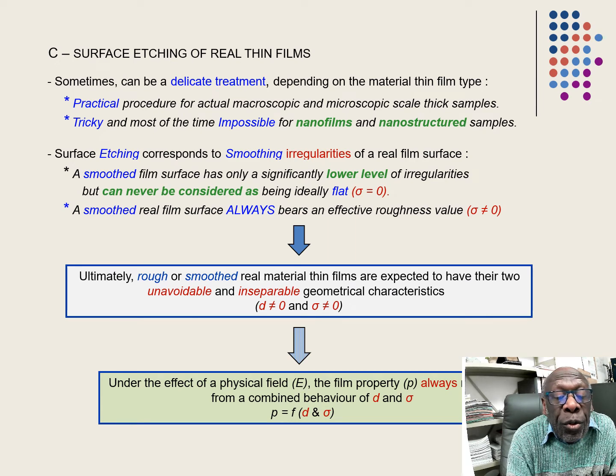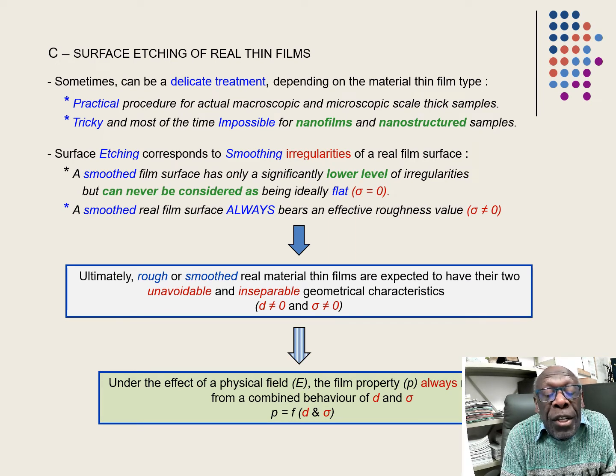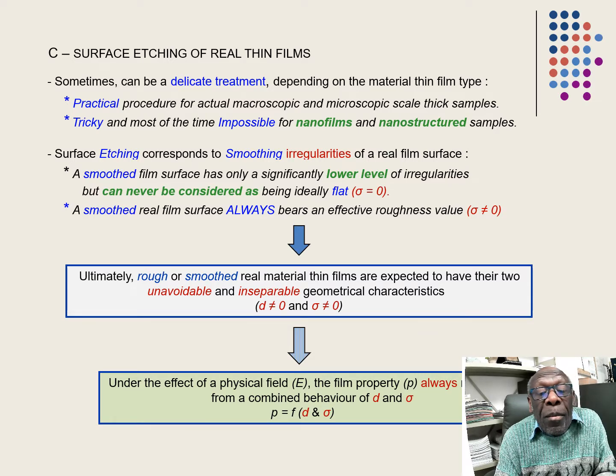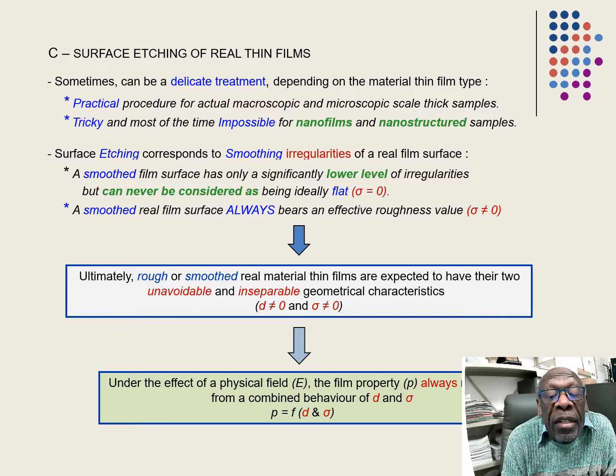That means you will just do a smoothing, but the smoothed or the initial samples, both of them are characterized by geometrical characteristics. That means D is different to 0, sigma is different to 0, always. If you try to measure your property, that will be the result of the combined effect of D and sigma. This is not sufficiently underlined in the physics of material thin films.